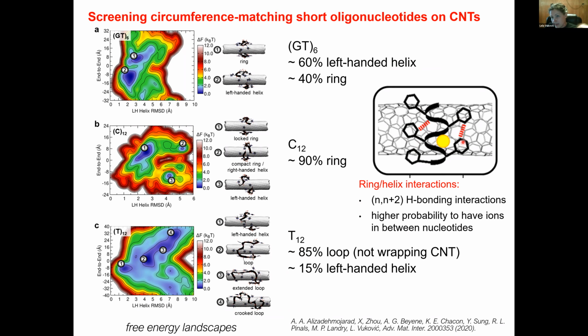Also, some sequences could have higher probability of having sodium ions inserted close to the backbone of the DNA molecule. We also observed that, and that should be leading the ring formation, such as in these sequences. So this was also published last year. This exploration of different sequence dependence on the ring probability of the ring formation of nanotubes.